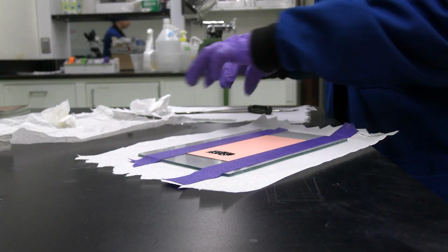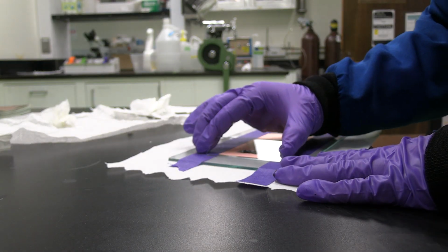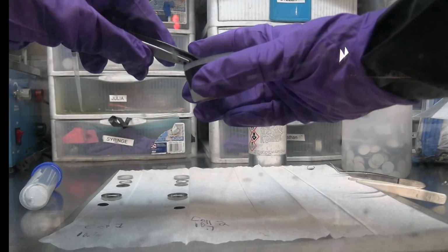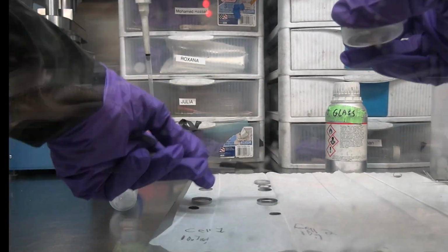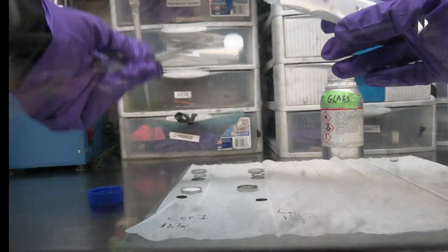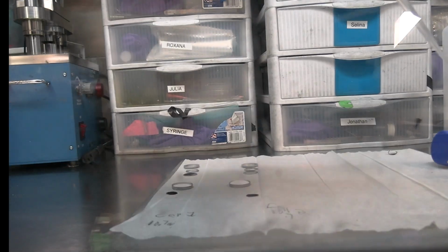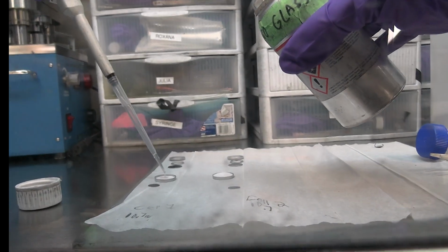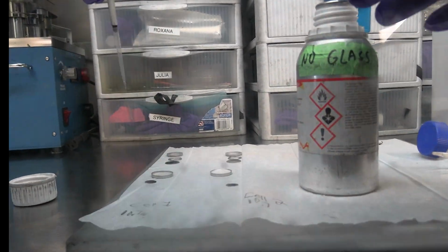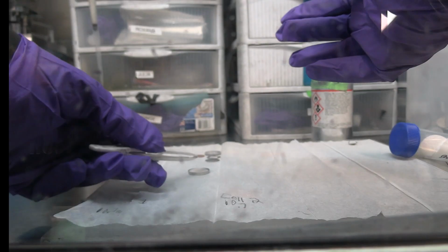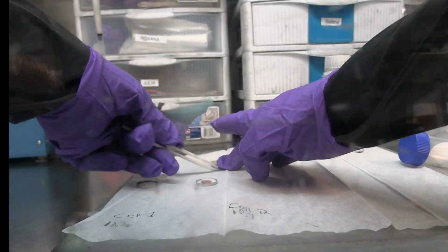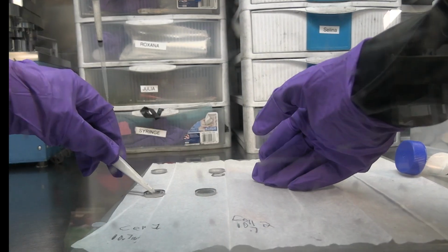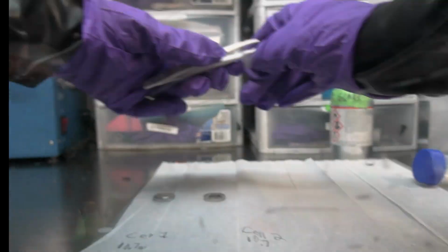We mix our hard carbon with a binder and more carbon to cast a slurry. After drying the slurry, we bring it into the glove box. When assembling lithium-ion cells, it is important to add a sufficient amount of electrolyte, which will allow the lithium ions to travel from the lithium disk at the positive terminal to our hard carbon material on the negative terminal. Once assembly is complete and the cells have been properly sealed, we take them out of the glove box and test their electrochemical properties using a potentiostat. Let's now see how this compares to commercial hard carbon.